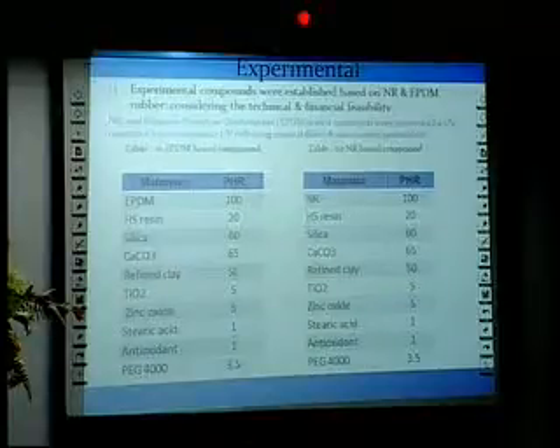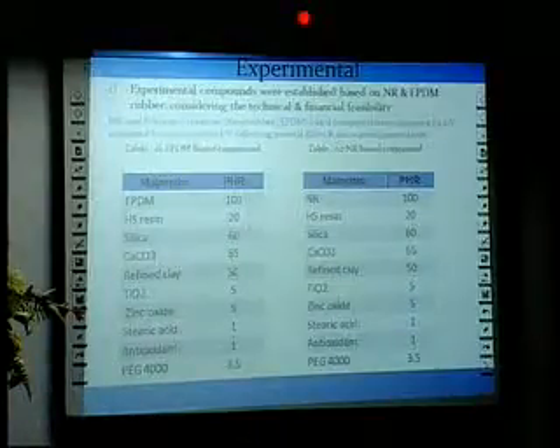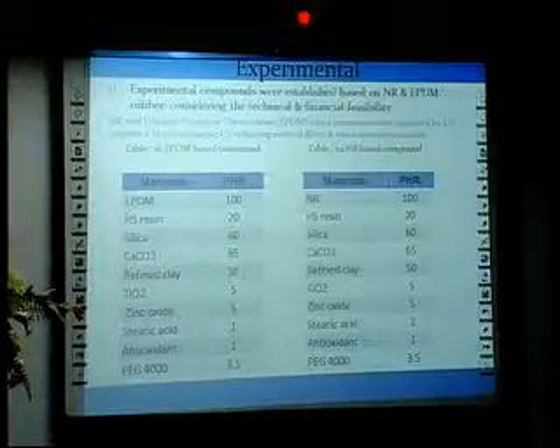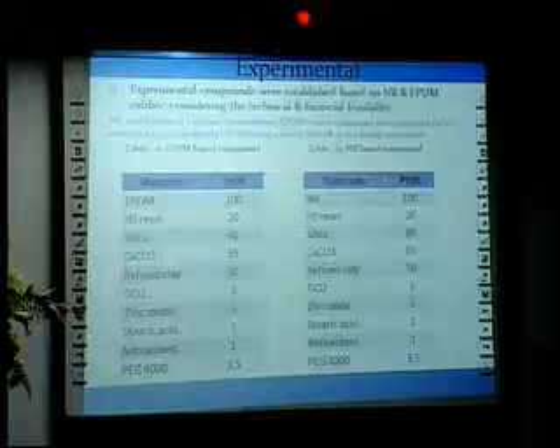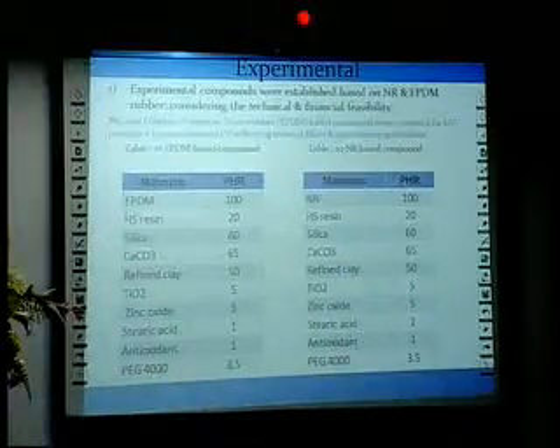Then we move to the experimental part of this study. First, the experimental compounds were established based on natural rubber and EPDM-based rubber. Here, you can see that Table 1 and Table 2 show the formulations developed for the EPDM-based compound and the natural rubber-based compound respectively. Mainly, the UV resistance was improved by incorporating UV-reflecting mineral fillers and non-staining antioxidants.